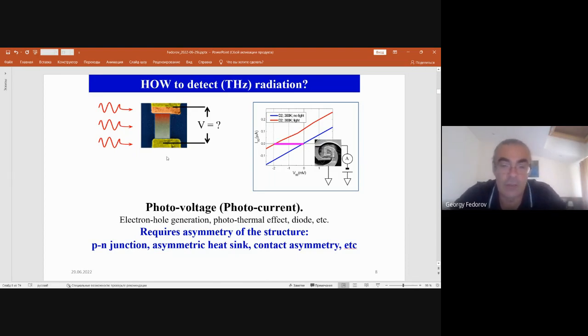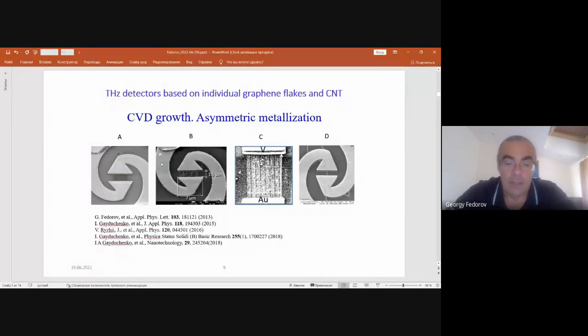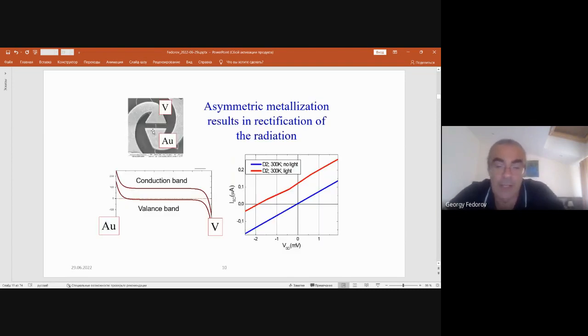You can also have a p-n junction inside the channel, so it will operate as a diode. Once again, this is what we have in solar batteries. And here are some examples of the structures we played with, asymmetric structures based on CVD-produced materials: carbon nanotubes, like here, CVD-grown graphene patterned into something, graphene patterned into nanoribbons, and also individual nanotubes. These are the hardest to work with because you always have to find them and then make the contacts. For these three, you just have a continuous layer of something, whether it's nanotube film or graphene, and you just pattern and put the contacts where you patterned your material. So these three are much easier to produce, but it turns out that individual nanotubes are the most responsive here.